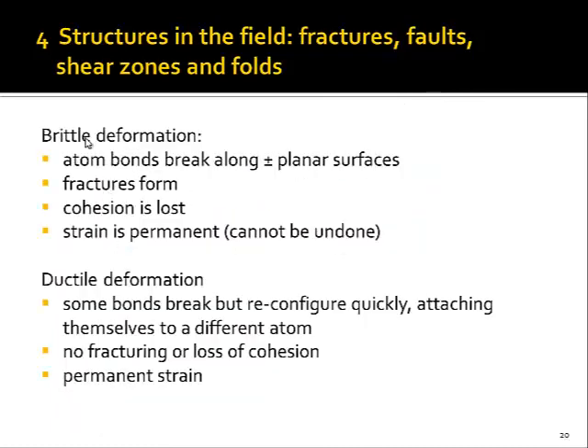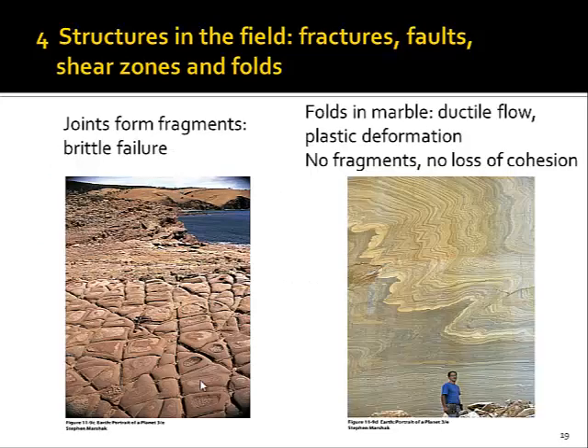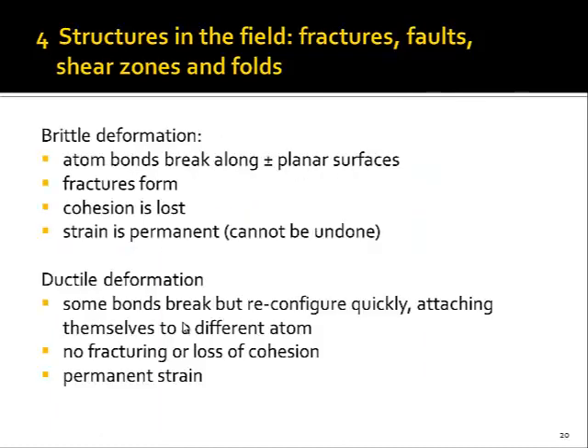So let's summarize the characteristics of brittle and ductile deformation. Brittle deformation leads to fracturing, and that requires that atom bondings are breaking along planar, more or less planar surfaces. Most fractures are reasonably planar, depending on scale you look at them. But if you look here at these joints, they are fairly straight, and in three dimensions they are more or less planar structures. We need to break all atom bondings along such surfaces in order to establish a fracture. That results in the loss of cohesion between the two fragments that have broken apart from each other. And this strain is permanent. It cannot be undone. Once you form a fracture, it exists.